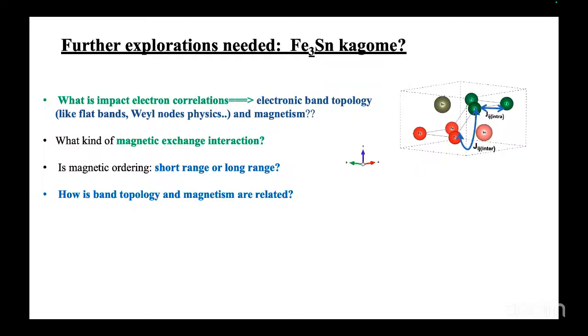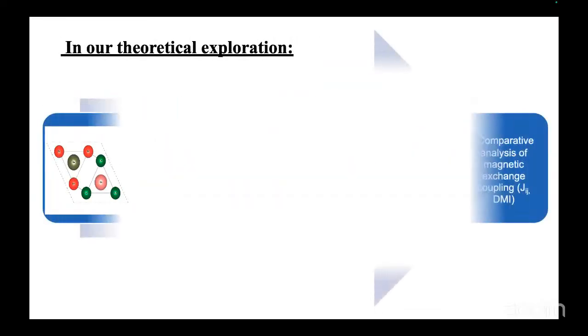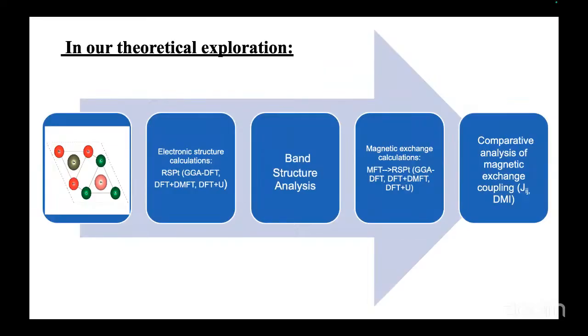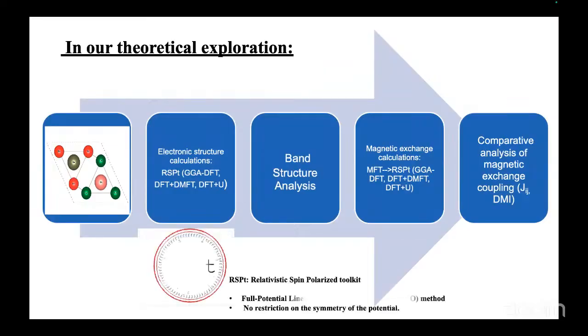With these broad questions, I did my theoretical investigation through electronic structure analysis using ab initio methods, that is DFT, DMFT, and DFT plus U, as implemented in the RSPt code. Then I did the band structure analysis, and further extracting the energies, I calculated the magnetic exchange interactions and did a comparative analysis of all these three methods. I will first go with my DFT results, and then how I proceeded further with DMFT and DFT plus U.